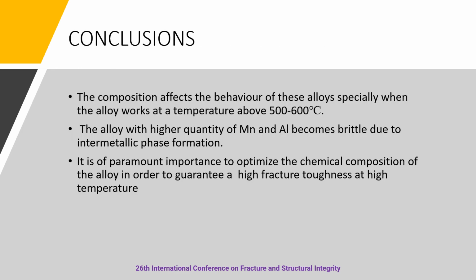So, in order to conclude, we can say that the composition affects the behavior of these alloys, especially when the alloy works at a temperature above 500 or 600 degrees Celsius. The alloy with a higher quantity of manganese and aluminium becomes brittle due to the formation of intermetallic phases. Lastly, it is of paramount importance to optimize the chemical composition of the alloy in order to guarantee a high fracture toughness at high temperature.